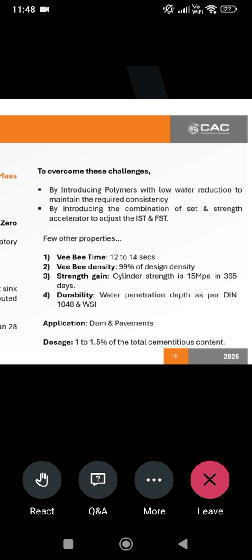VB time is 12 to 14 seconds. VB density, 99% design density. These are the specifications. Strength gain: it is very low grade concrete like M15, and it is tested in cylinder, not in cubes. So in 365 days, 15 MPa strength is required. Durability, water penetration. I'm talking about dam concrete, right? Dam mass concrete. Durability, water penetration depth as per DIN 1048 and WSI has to be checked. Dam and pavements, 1 to 1.5% of the total cementitious.